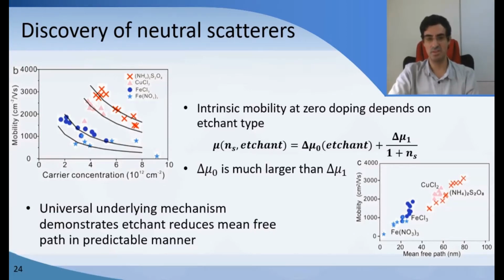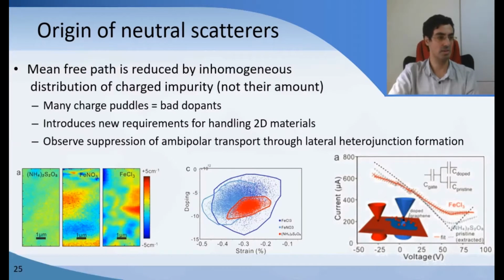And so we're conducting Raman spectroscopy and statistical analysis of Raman data. We get maps, and we see that the ammonium persulfate has a very uniform distribution of charge transfer. We can map out the charge transfer between graphene and adsorbates by Raman position. And so we see that it's pretty uniform for ammonium persulfate, whereas iron-based etchants have very non-uniform distributions of charge transfer. So you're getting these charge puddles of highly and lowly charged regions. And so it seems that this is the hallmark of a bad etchant. It's not about how much charge they're introducing.